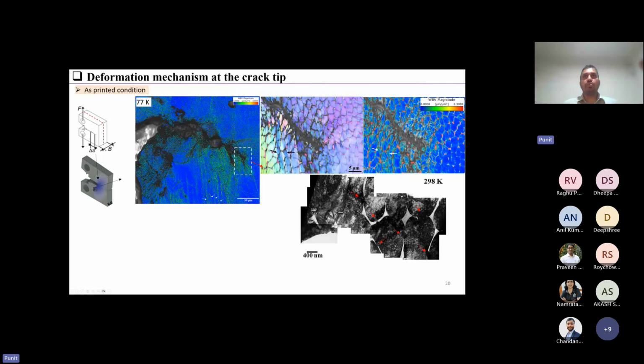And if you look closely, you can see these misorientation bands are actually traveling in between the B2 phases on the cell boundaries. And if you do TEM, you can see the same thing again here, where you had these nano bridges of dislocation, these openings break down, and you can see dislocations traveling through these openings, these channels, and they are traveling further away from the crack tip.